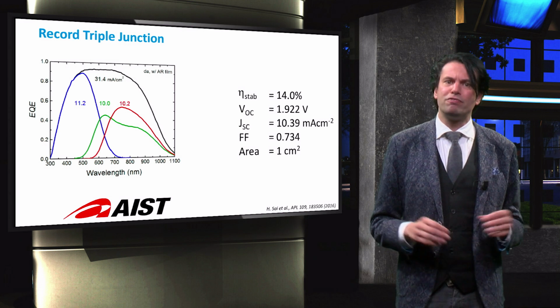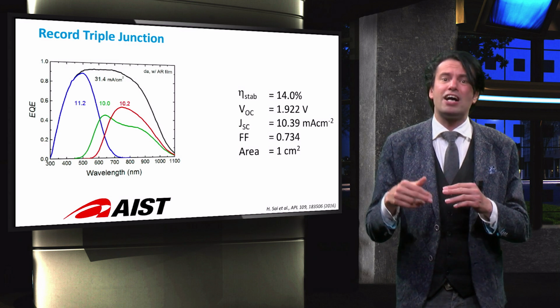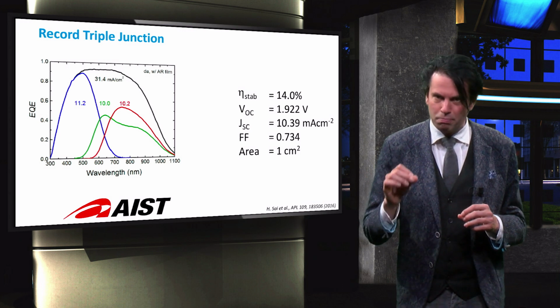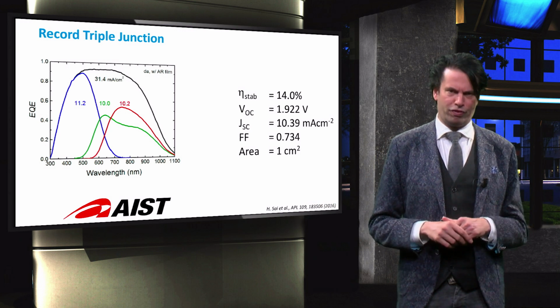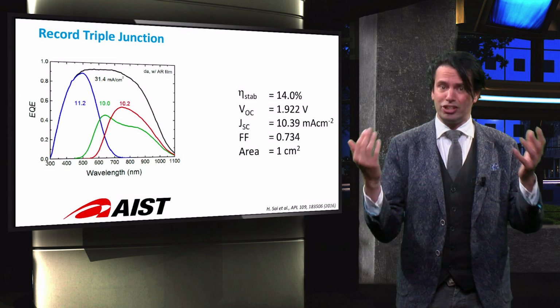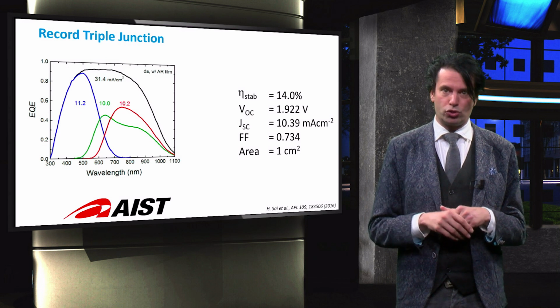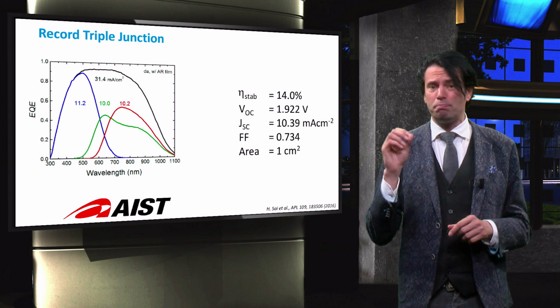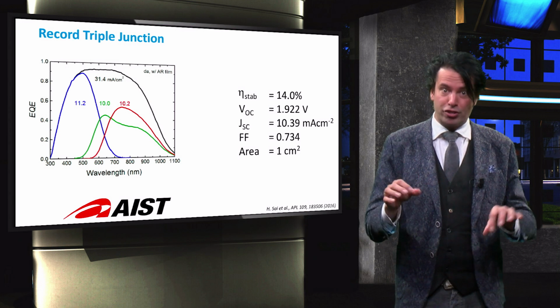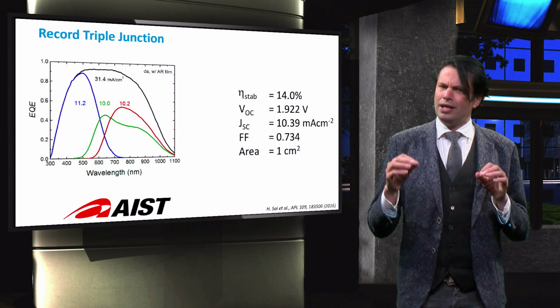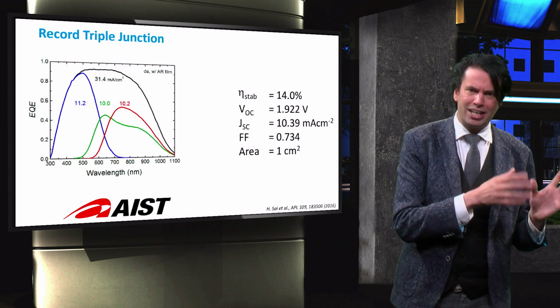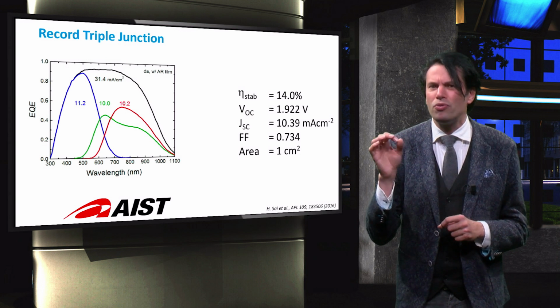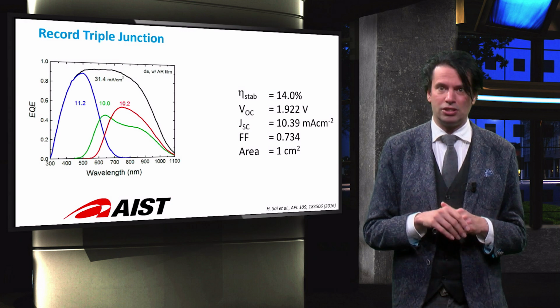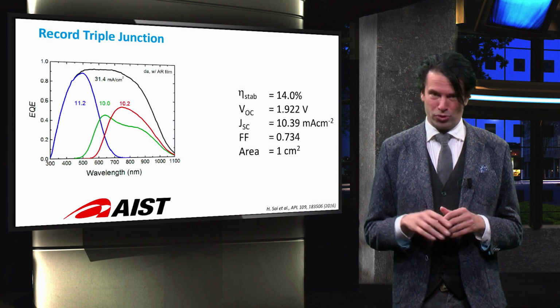As you can see in the EQE of this triple junction cell, the top cell generates by far the highest current. This means that the fill factor is not limited by the amorphous silicon junction with the poorest individual fill factor. As a result, a relatively large value for the fill factor is obtained for the triple junction solar cell. The stabilized efficiency of 14.0% is currently the record conversion efficiency for thin film silicon devices. Interestingly, the combination of high-quality amorphous silicon and the current mismatch results in an extremely small difference between the initial and stable conversion efficiency. This relative difference is only 4%. We will continue our discussion of the state-of-the-art thin film silicon multi-junction devices in the next video.